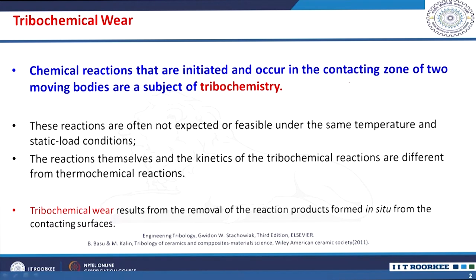When you have two bodies moving relatively and in contact, there can be a reaction happening at that contact, but they are subjected to sliding or wear conditions. What happens? There is a synergetic effect of mechanical wear. At the same time, the chemistry also plays an important role. So, you will have a synergetic effect of this chemistry as well as this mechanical wear. The tribochemistry playing a role in material removal is what we call tribochemical wear.